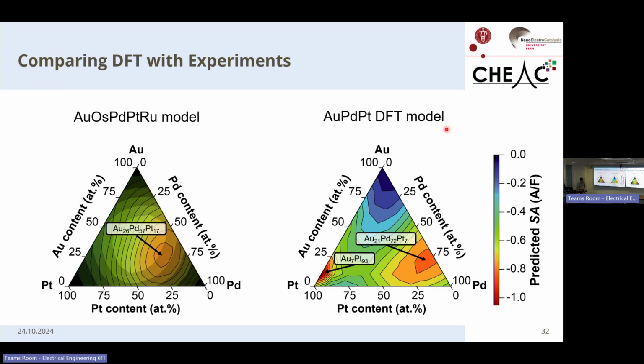So for this work, we decided to limit ourselves to the most active subspace, which is the gold, palladium, platinum subspace. And the DFT calculations demonstrate that there is a local optimum at a similar location as the optimum predicted by the 5-element space. However, the DFT calculations also show that there is a global optimum in the platinum corner, which we are missing in our Gaussian process. The Gaussian process also has an associated certainty to its predictions, and this is the one you can see in the circular overlay. So basically, in this corner, we have no certainty in our prediction, and this has to do with the fact that there are no experiments in the corners.